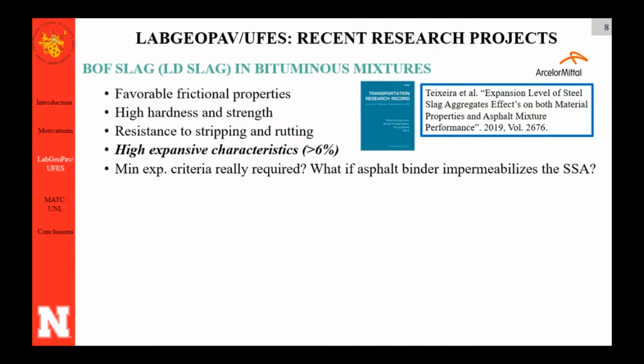However, one of the reasons that people in Brazil still think that they cannot use slag as a material for pavement construction is because of the expansion of this material, if this material gets in contact with humidity and hot weather, heat. With heat and water, this material can expand. So they think that if we put this material as an aggregate in a pavement structure, we can develop internal stress that will trigger cracks on the pavement.